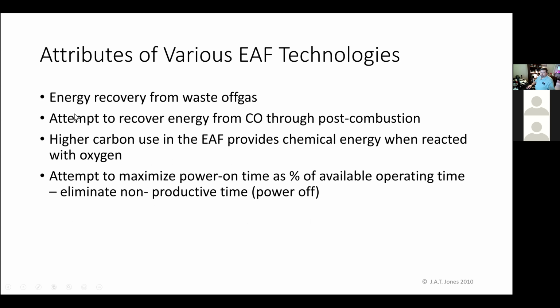So what we did was we started to develop technologies to recover energy from the waste off gas, to post-combust CO that's generated in the furnace to CO2 to recover that additional energy, using higher carbon use, which would allow us to input more chemical energy concurrent to the electrical energy input, and then things like maximizing power on time as a percent of the available operating time.